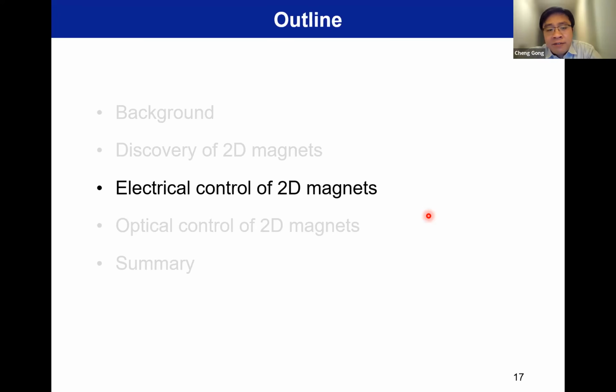But each surface has 10^15 atoms usually. So that means for each surface atom, you only modulate the electron concentration by 0.001 electron to 0.01 electron. So that's fractional. Of course, some people will say maybe use the ionic liquid. That's very complicated. Sometimes the ion can easily penetrate there and distort the atomic structure. That's out of the scope of discussion here.